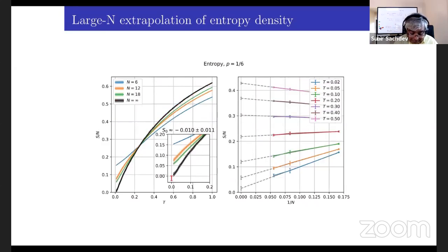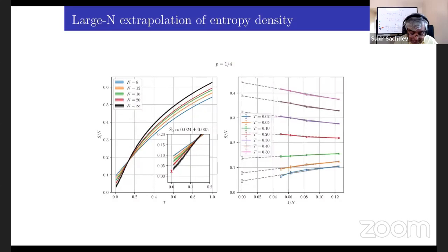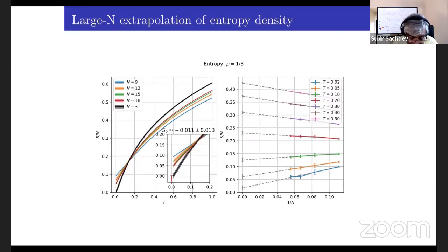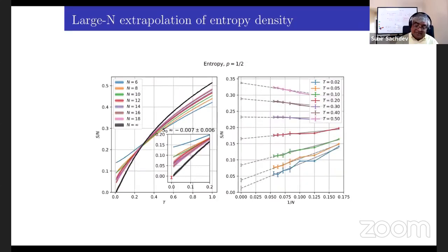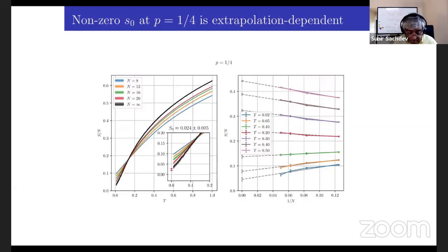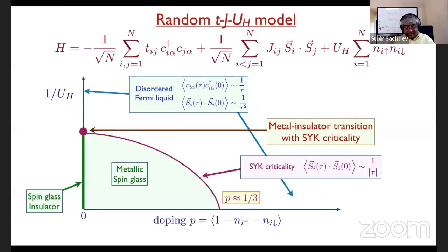And then you increase the doping, p equals 1/6, the entropy is still going to zero, extrapolating to infinite size, but right at 1/4, depending on how you do the extrapolation, in some extrapolation you do seem to find a small non-zero zero temperature entropy. But if you do a slightly different extrapolation, it disappears. And once you go to higher doping, there's no sign of it. So anyway, there's some evidence, I would say, and not anything more than that. The entropy certainly has a maximum that we are pretty confident about, but whether it has a zero temperature entropy, we can't conclude, but there are promising signs, let's just say, at this point. Okay. All right, so that's basically the end of my talk.